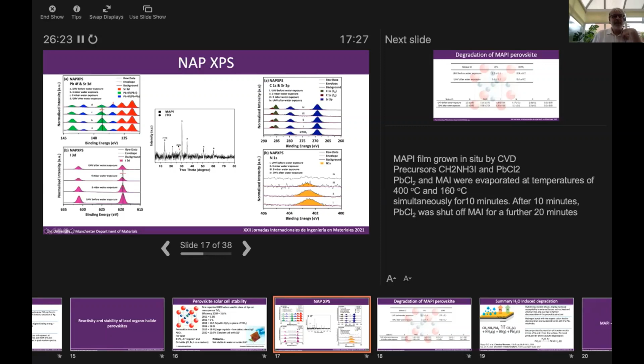When we pump away the gas and we measure again, we can see that there's a substantial decrease in the intensity of the lead. It's still shifted to a lead position consistent with lead iodide, and we've got more metallic lead in there. So this is suggesting we're getting conversion first to lead iodide, and then the lead iodide is decomposing to form lead. This is a known reaction, the photocatalyzed reaction from lead iodide to metallic lead. It occurs in the presence of moisture and photons greater than a few electron volts.